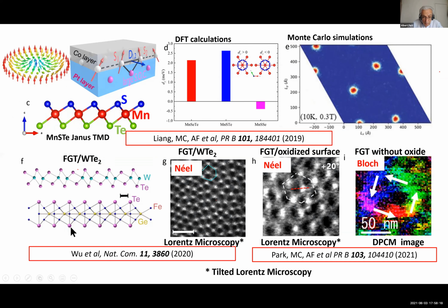First, this very beautiful result has been obtained at UCLA by inducing the Dzyaloshinskii-Moriya interaction by depositing this TMD, transition metal dichalcogenide, on FGT. This is FGT and this is TMD. And so this introduces, of course, an interface and a breaking of the inversion symmetry, like in this picture, where now the symmetry breaking is at the interface. And this is the result they found: Néel skyrmions induced by the Dzyaloshinskii-Moriya interaction. This is a typical image of tilted Lorentz microscopy, with a classical image of skyrmions corresponding to this double moon, white and black moon, in this way.